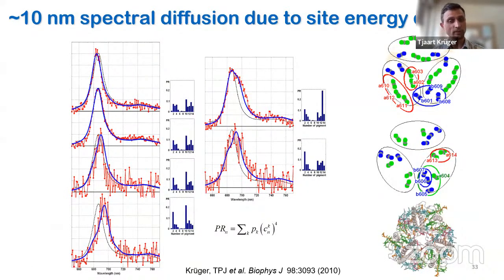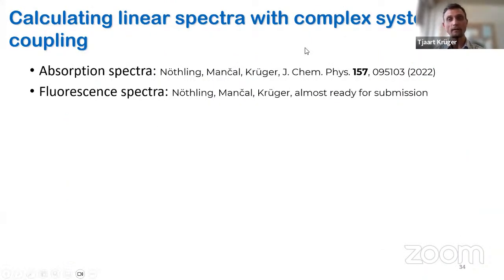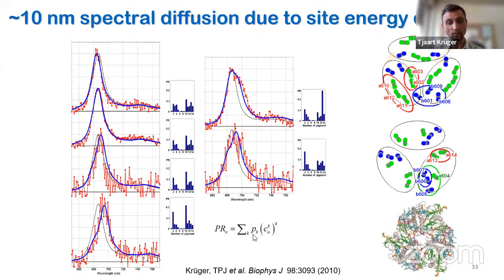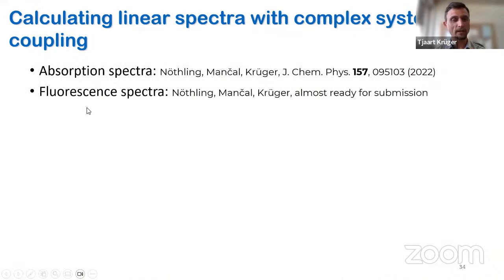Okay, and in the meantime, we've also taken this model further because this is a complex system. It is not trivial to model them, especially if you consider the fact that the system bath coupling is pretty complex. There are a lot of distinct vibrations in the system, a lot of different dipoles that are interacting. So it is not trivial to calculate these spectra. One has to make a lot of approximations along the way. And last year, we published a paper where we compared different approximate methods to calculate linear absorption spectra, and we compared the cost and efficiency of these different methods, and we illustrated that a model, for example, what was used here, modified Redfield, is actually not a very good model to use. There are better models to use. Currently, we are applying the same principle to compare different approximate methods to calculate fluorescence spectra.